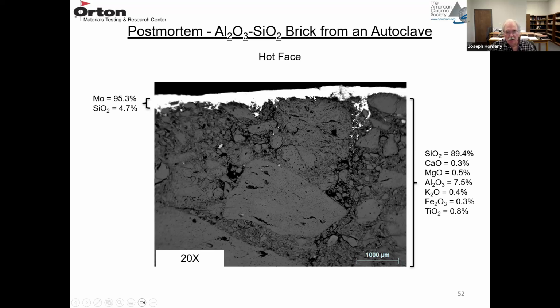So you can see right at the hot face, this bright region is some residual MO and a little bit of silica. So here's the residual metal right at the surface. Some of it has diffused into the refractory in the matrix. So the chemistry here is about 90% silica, maybe 7.5% alumina. And then you have your typical impurities, CaO, MgO, K2O, Fe2O3, and TiO2. This did not start out as a high silica refractory brick. The alumina has been attacked in this refractory.